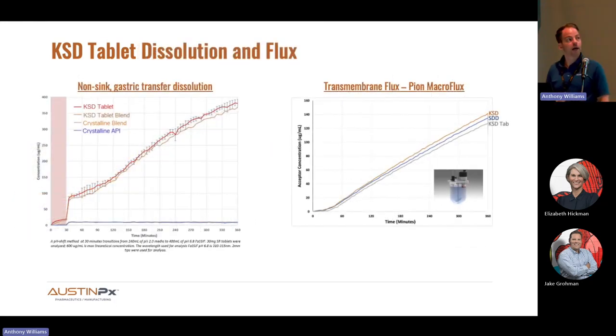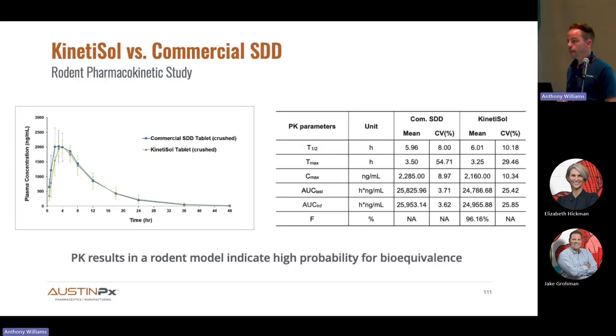So once again, using our Pion tools, we're able to show with pH change DISO that by developing a tablet, we didn't alter the dissolution profile of the ASD intermediate, and then running flux between the KinetiSol intermediate and the spray-dried dispersion, we showed very similar flux profile from our tablet. And then finally, this all culminated in an animal PK study. In this case, we did a rodent PK where we took the commercial tablet and pulverized it into a powder and dosed that against the equivalent of our KinetiSol tablet. And what you see qualitatively, if you could see it, is the PK profiles lay virtually on top of each other. And since that doesn't look so clear, you can look at this F%. We're about 96% of the commercial tablet. So there are some next steps involved here in further establishing this, but I think we're off to a good start in terms of establishing there's a high probability of success that we will be able to duplicate this commercial spray dried product with KinetiSol.